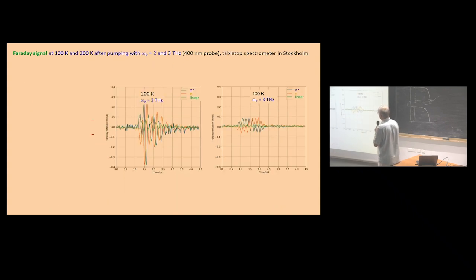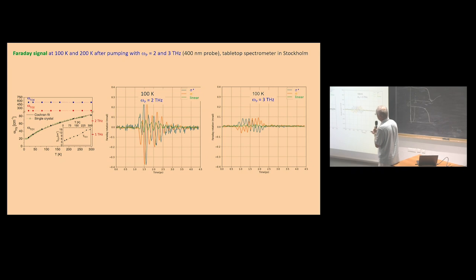When we measured it at 100 Kelvin, pumping with 3 terahertz gives a weak signal, but if you pump it with 2 terahertz, it's a much stronger signal. Again, it corresponds to this, that if we are at 100 Kelvin, we are close to 2 terahertz, and we can see this magneto-optic Kerr effect.